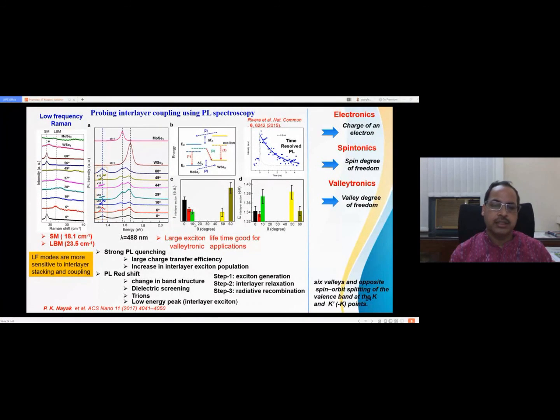You can see that close to high symmetric stacking, like 0 and 10 and 50 to 60, this interlayer exciton exists, but the coupling strength, we speculated at that time, might be decreased in this case. That's why we are not getting this one. So what is interesting if you get the interlayer exciton? What is the application? People will ask. It is a very emerging application in the case of Valleytronics material.